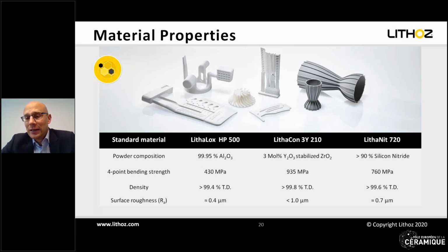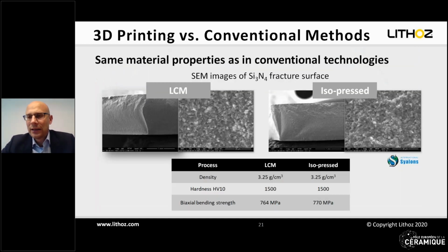And this shows you that these values are very similar, if not the same, as in conventional forming technology. One of the most difficult materials is silicon nitride, as you already know from conventional ceramic forming technologies. And here, let me show you just a comparison. If we compare LCM to an isopressed part, with the same powder and the same sintering cycle, basically you can see that there is no difference. The microstructure is the same, and the material properties are the same. So basically you cannot tell from these pictures whether this has been made by additive manufacturing or not.